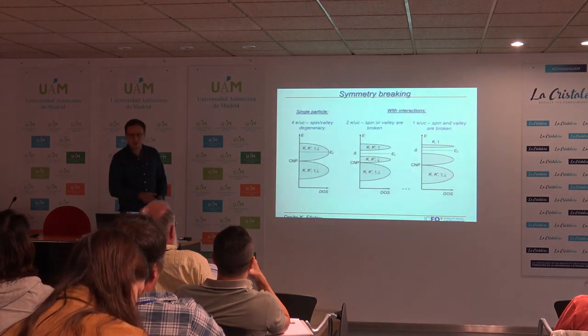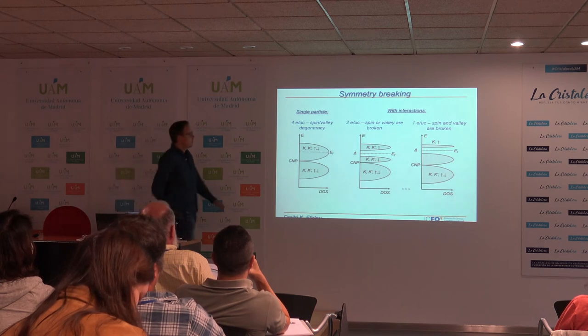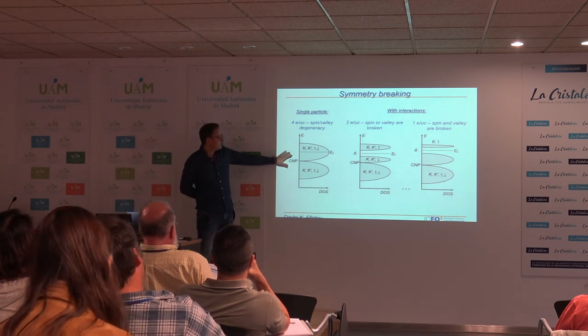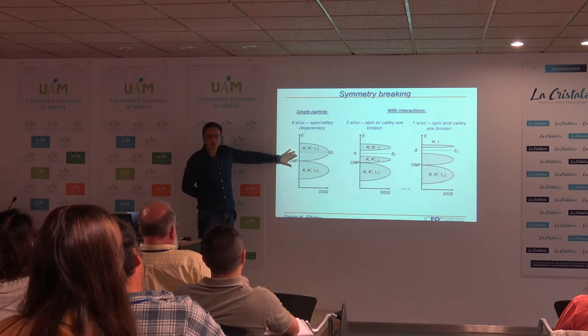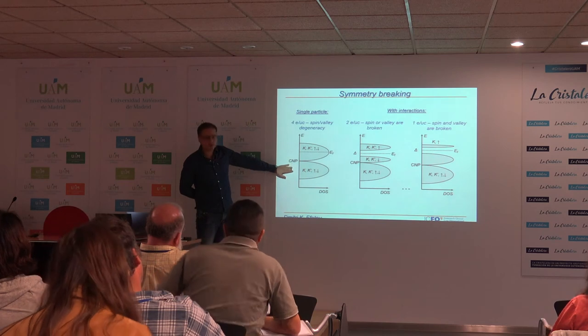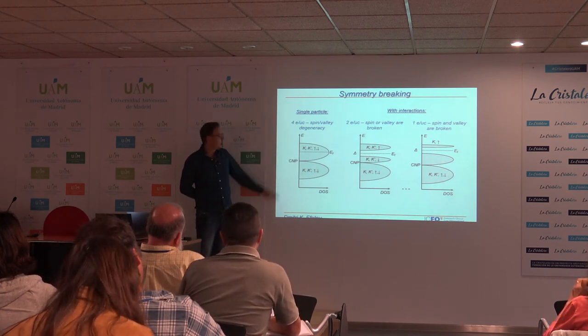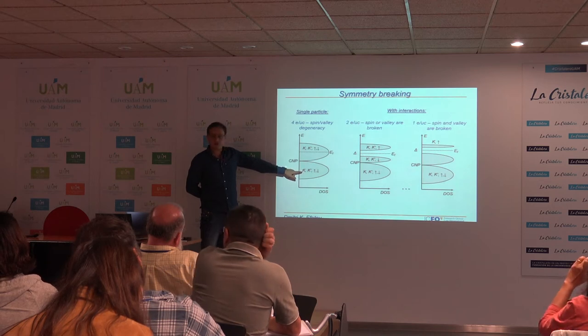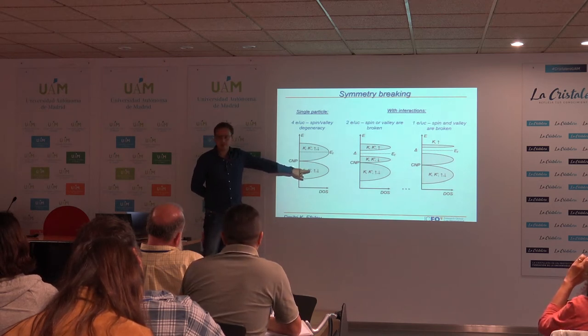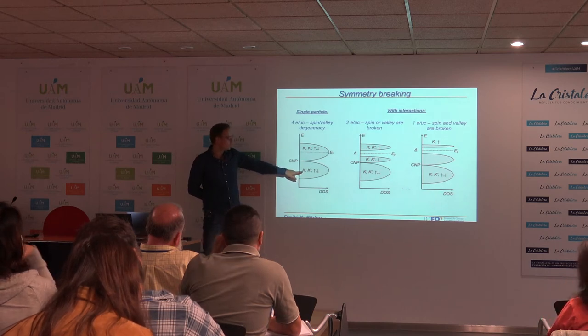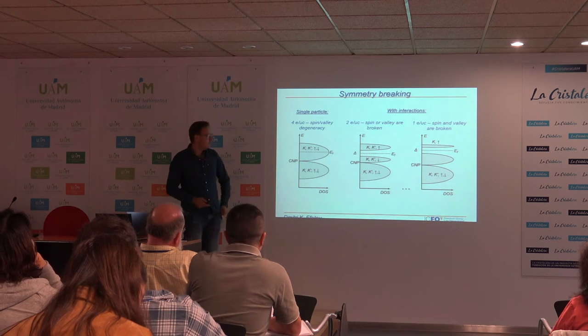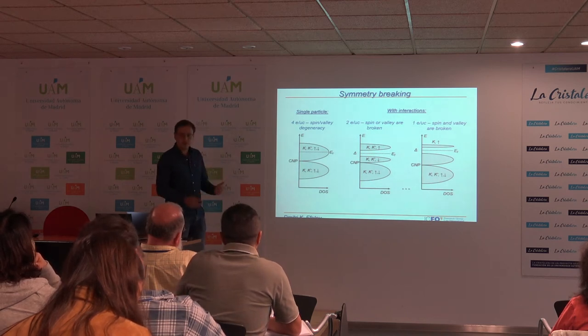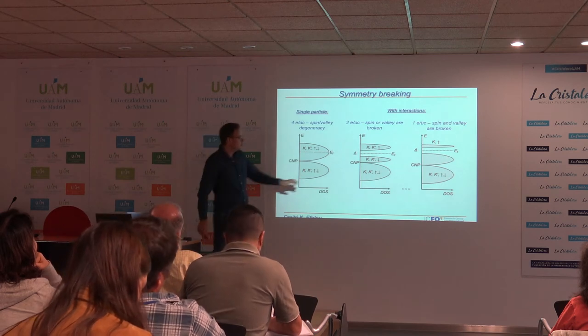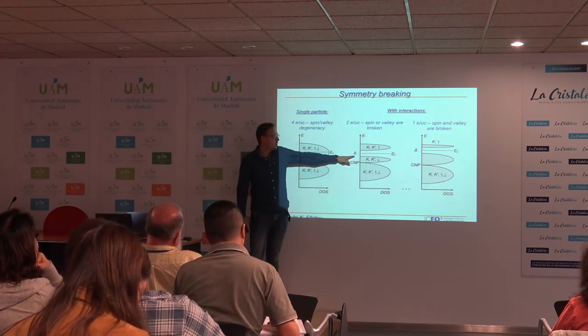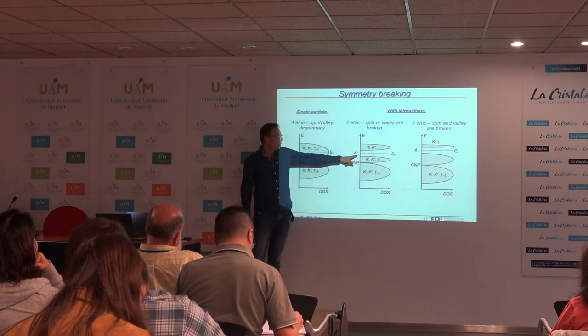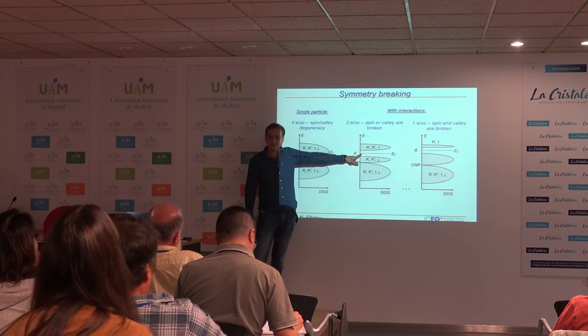So this is sort of my understanding of what's happening. As Pablo was explaining, in a single particle picture, you basically can think of it in the following way. So you have this valence band and conduction band. In the valence band, both bands are fourfold degenerate. So you have K, K prime, spin up and spin down, where K again corresponds to valley degrees of freedom. And then, of course, in the case of half filling, if you take interactions into account, this is what can happen. In principle, you develop this interacting gap in this case in the conduction band if you tune the Fermi energy to half filling.